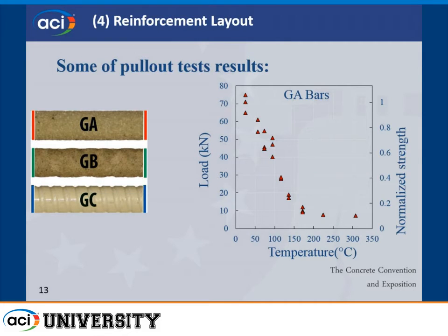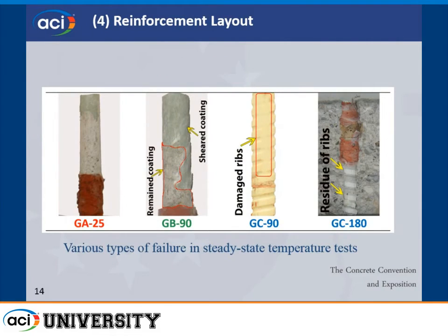But there still always seems to be a little bit of bond strength. So perhaps if you have longer anchorage, it works better. Here, we had 8 inches or less, and it was still enough to hold the loads. These are some of the failure modes that we got when we did these tests on the material testing, so they're largely dependent upon the polymer.